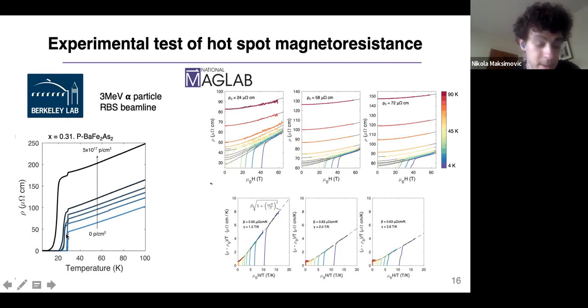Yeah, so that is a good question. I think one answer could be that we're not in the right regime of temperature. Maybe you expect to see the strongest changes to the temperature-dependent resistivity below 30 Kelvin. Another answer is that the hot spot, cold spot model is not the correct description of the T-dependent resistivity. Right. Yeah, it's difficult to say whether the disorder will affect the temperature-dependent resistivity in this low-temperature regime.